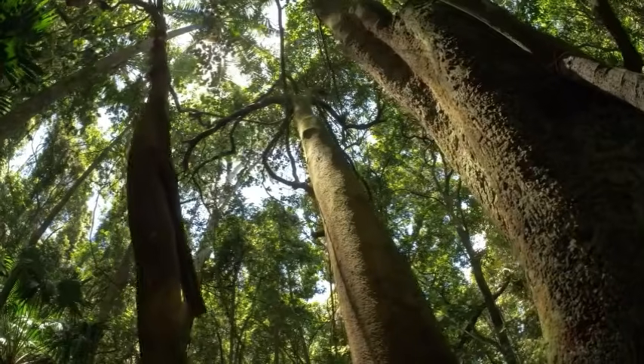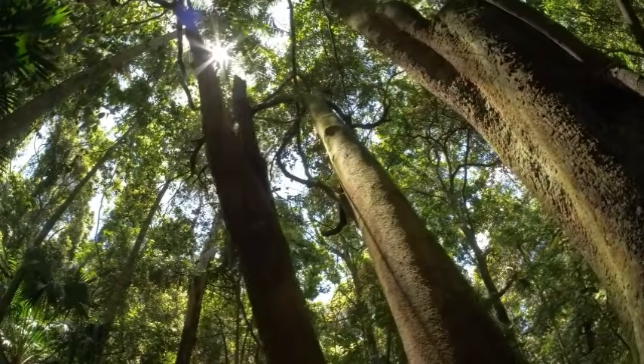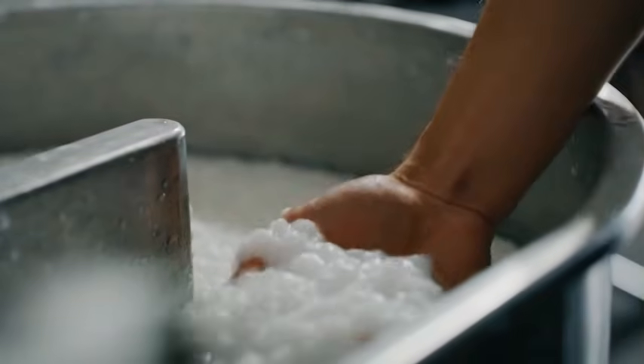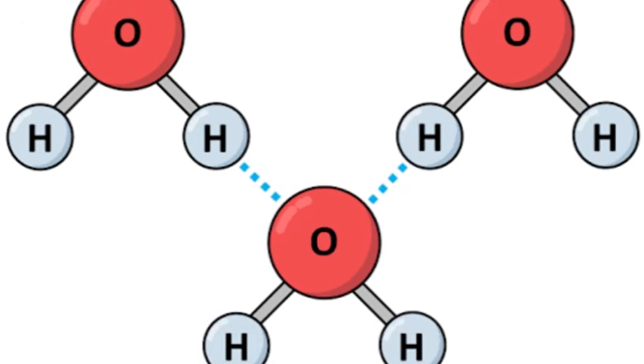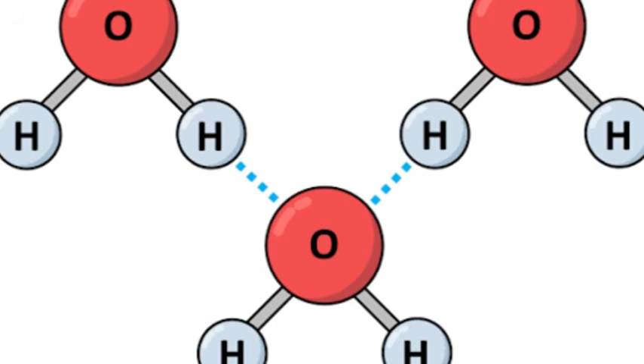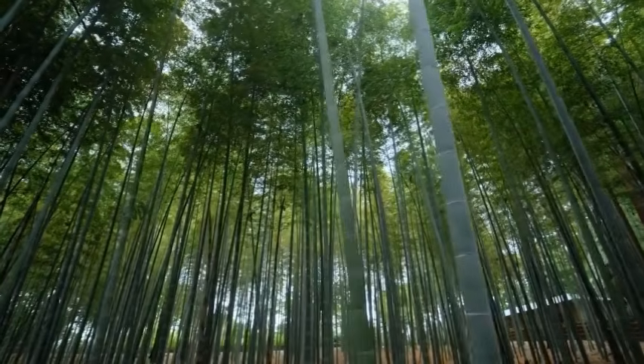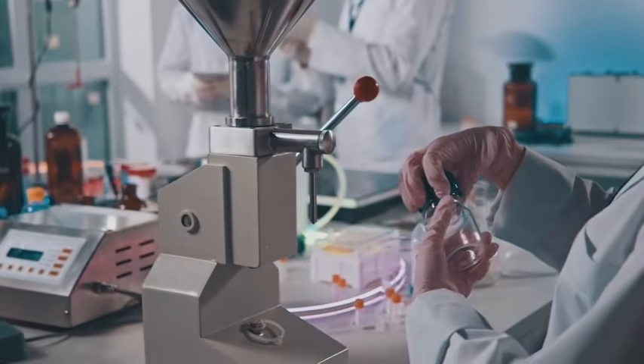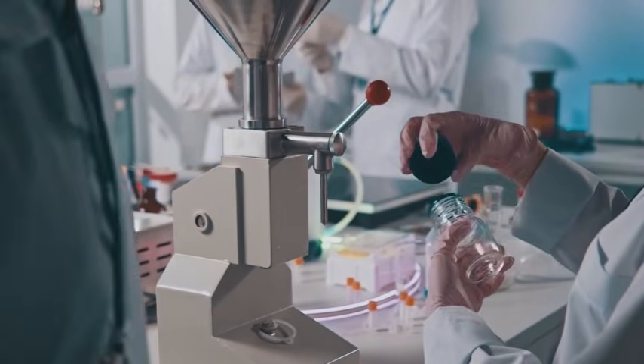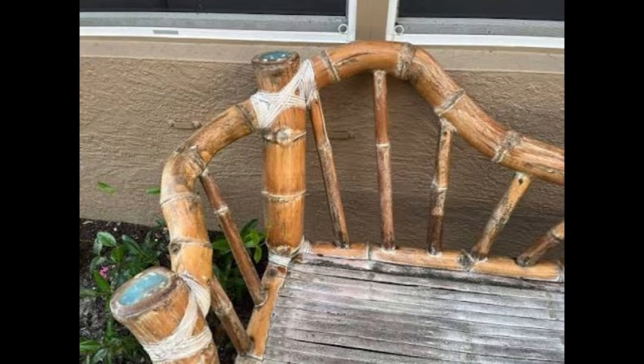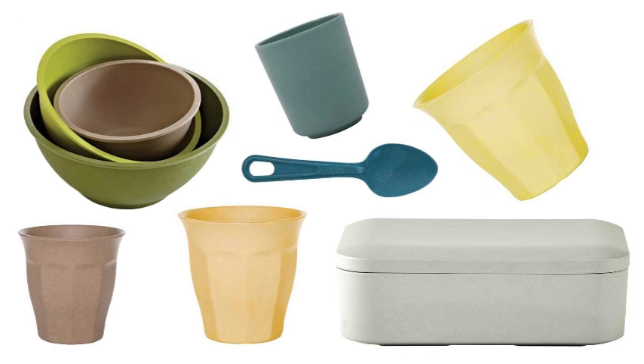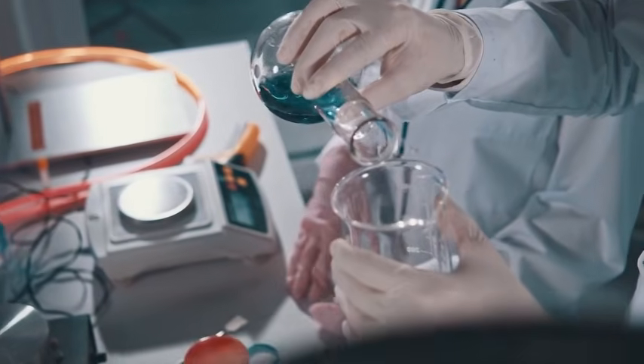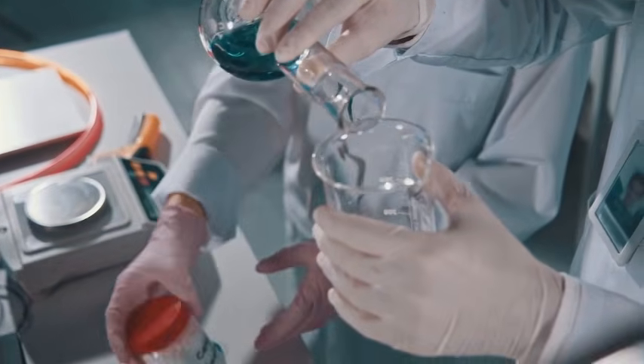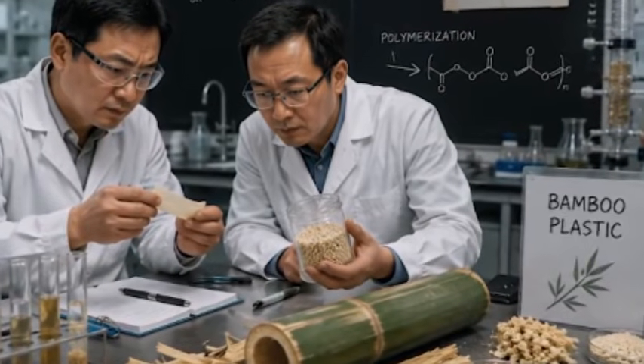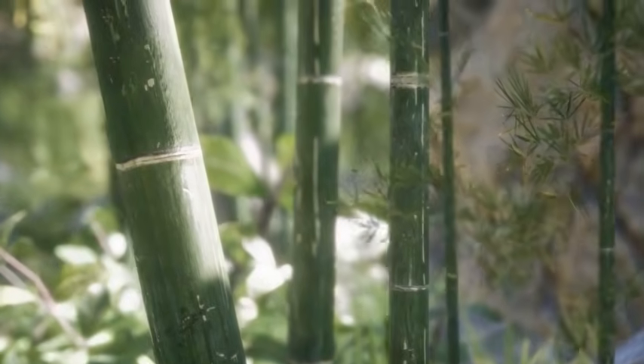Here's why bamboo was considered basically impossible to work with before this. The cellulose inside bamboo is locked together by an incredibly dense web of hydrogen bonds, which is what lets a bamboo stalk stand tall in strong wind, but those same bonds make it almost impossible to reshape. Try to force raw bamboo into a mold and it just snaps. Earlier attempts at bamboo plastic cheated around this by grinding up bamboo fiber and gluing it together with regular plastic resin. It looked green on the label, but it was still half oil, and it still didn't biodegrade.